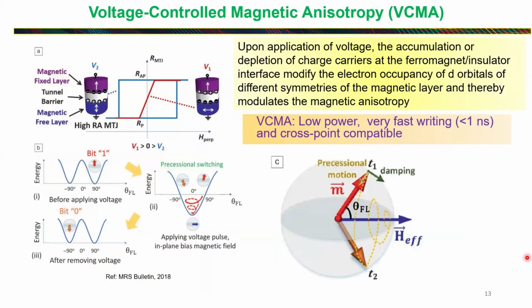Basically, if you make a perpendicular magnetic tunnel junction, at the interface you have interfacial perpendicular magnetic anisotropy, and because of that your easy axis is out of plane. So you have a perpendicular magnetic anisotropy that's coming from the interface between the cobalt iron boron and MgO. If you apply an electric field, that means you drop some electric field across the interface, and that electric field can modulate the electron occupancy of the d orbitals, and hence it can modify your magnetic anisotropy. So if you can manipulate this magnetic anisotropy with voltage, then you can use this for basically MRAM technology. So how exactly does it work?